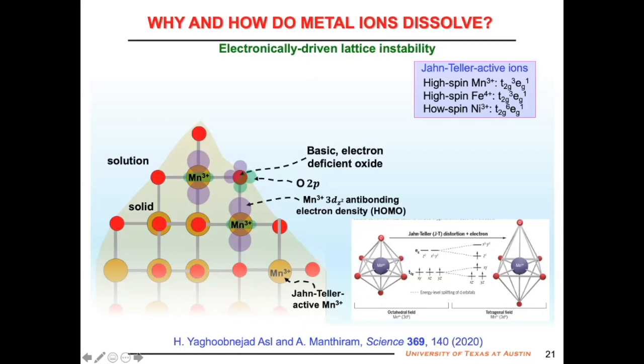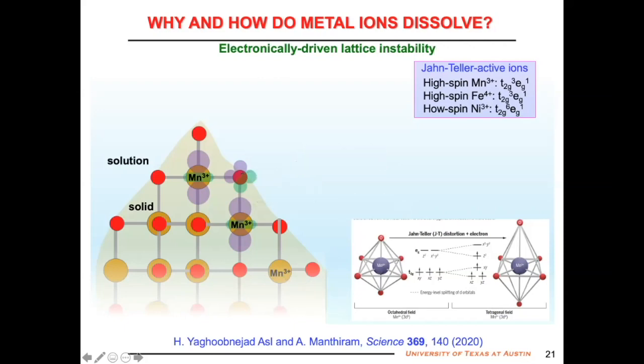Particularly metal ions which have one electron in the eg band are Jahn-Teller active. They can have long range distortion or dynamic fluctuation, Jahn-Teller distortion. If you have that, then a few things can happen. The Mn3+ ions can do charge ordering to relieve the instability. So one can become 2+, one can become 4+.